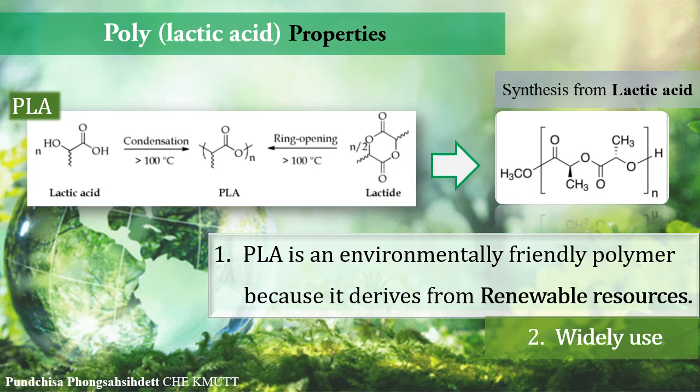Let's start with PLA. PLA, or polylactic acid, was synthesized from lactic acid. This type of plastic is the most successful of the biodegradable polymers. Main properties of PLA are brittleness, which is a huge problem to form PLA in other applications. PLA also has low crystallization rate and low glass transition temperature.